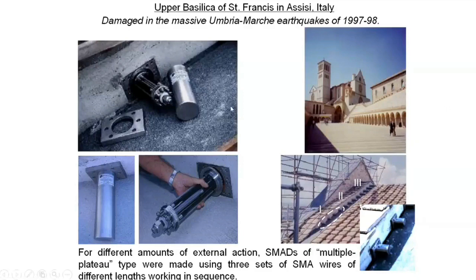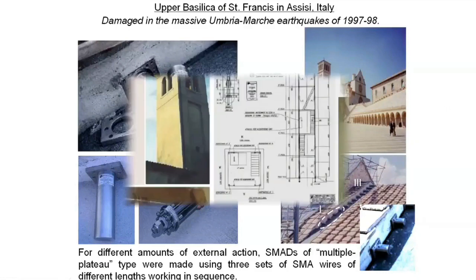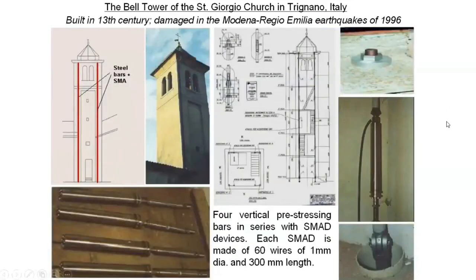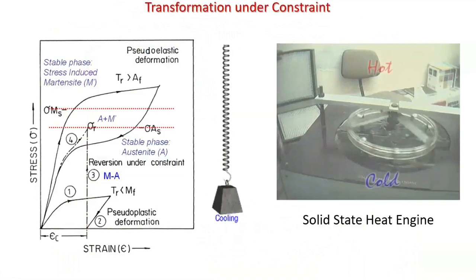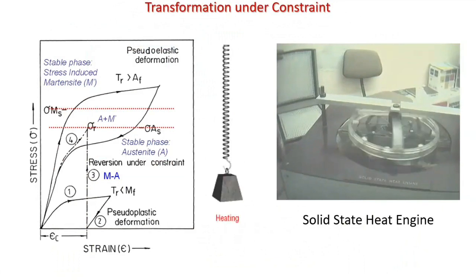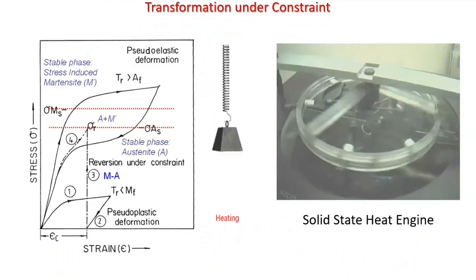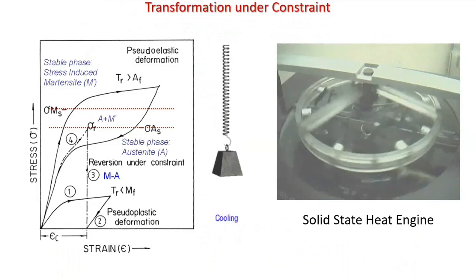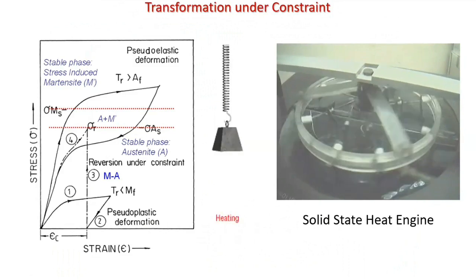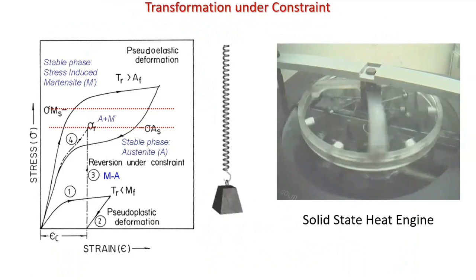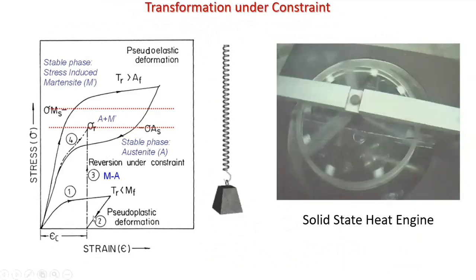So you can see here, what they've done is again use the principle I mentioned earlier, a combination of superelastic and pseudoplastic material, and they have made such devices. And maybe the next slide also shows one such tower in which you have set up these ropes of nickel titanium to absorb the energy. So you have the seismic event go by and the structure is intact. So that is one kind of application. But so far we discussed two: superelastic and the ones which are free recovery. That means you deform it and it comes back to its original shape.